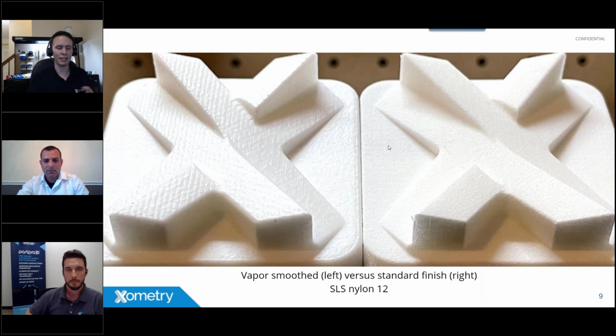Compared to the right-hand side here, this would be a standard finish: grow, clean, and ship. And this has that much more matte, sugar cube-like feel. The one caveat I'll say is that these were actually built at different times. I built these at different orientations. I like this orientation better. I built this afterwards, and that would actually mitigate a lot of those lines there. So this could be even smoother if I built it on the corner like I did with this one here.